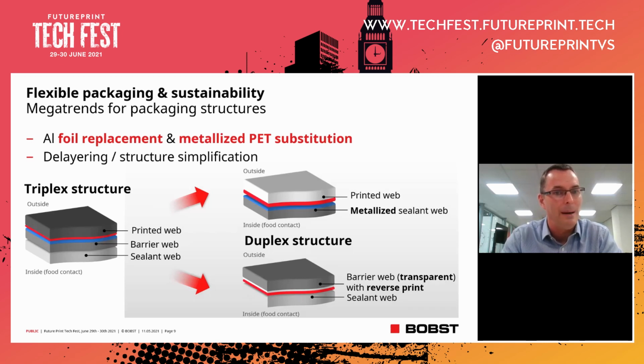3-layer triplex laminate. The upper web is based on a printed substrate or web, which in this case, we use a reverse printed concept. The middle web is a barrier web using an opaque, shiny, metallized barrier layer as a way to provide the barrier functionality. And the bottom layer is the lower sealant web, which has been designed to offer the correct seal performance or window needed for the packaging application.